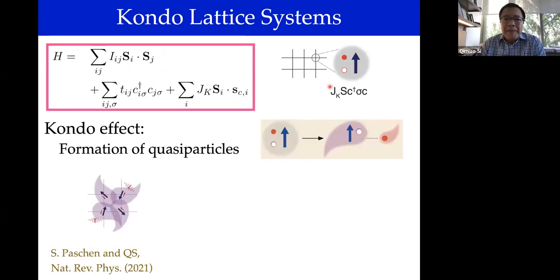Now, it has been a long-standing effort of the correlated electron community to recognize and to develop the formalism of describing the formation of quasi-particles from the Kondo effect, which imagines that the local moments, instead of forming antiferromagnetic order, form a singlet with the conduction electrons as depicted by this qualitative picture.